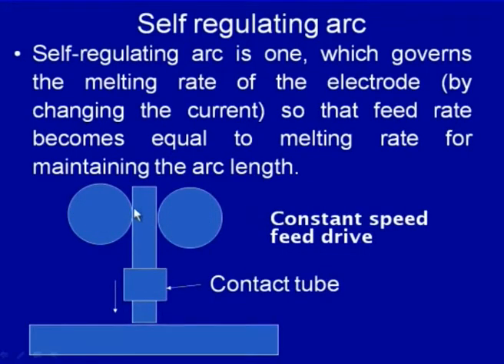And for this purpose, the electrode is fed using a constant feed drive system, and the gap between the two is maintained closely with the help of the self regulating arc. To look into greater detail of the mechanism through which the self regulating arc is maintained, we need to see that if there is any fluctuation in arc length due to any reason, it will change the welding current, especially when we are using the constant voltage type of power source.